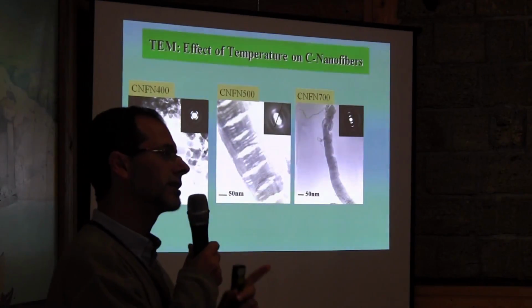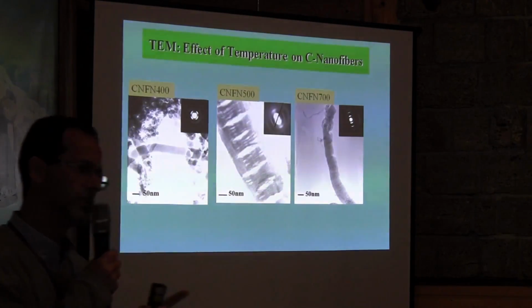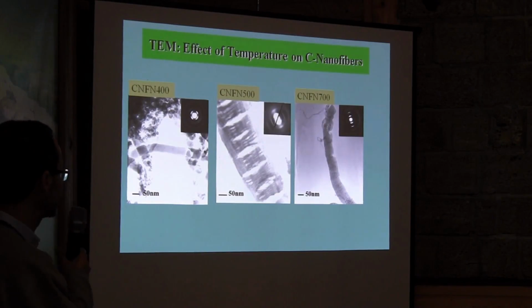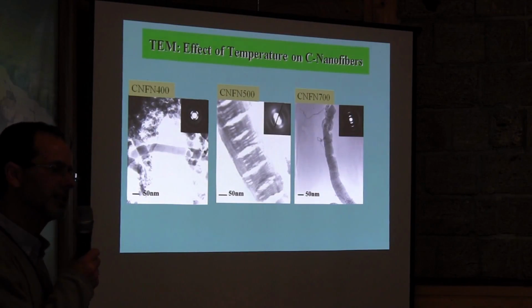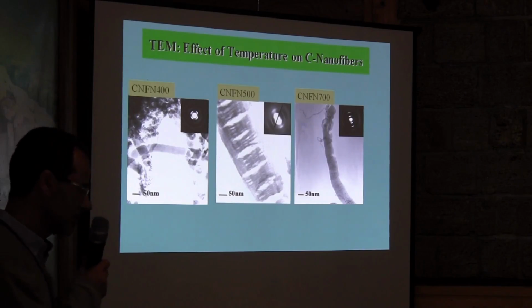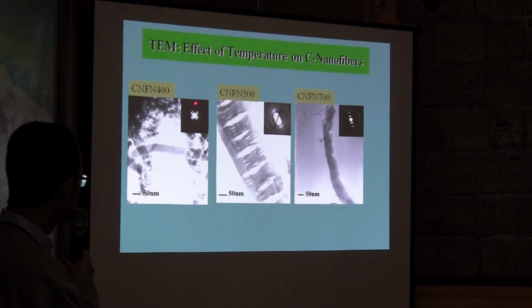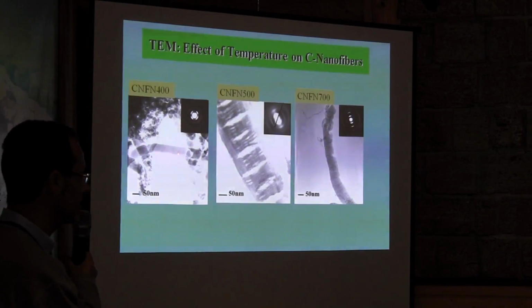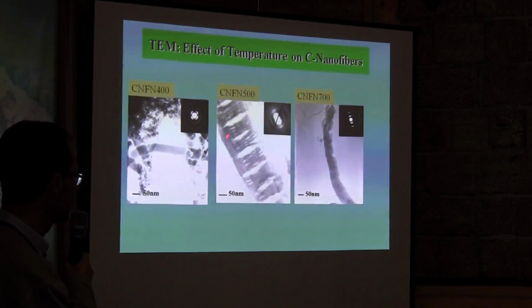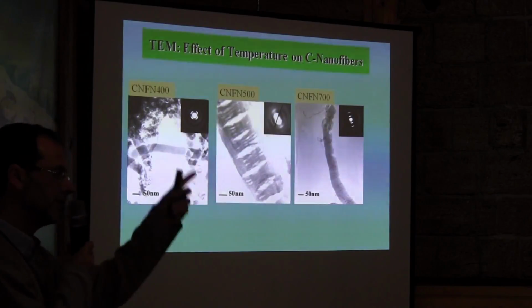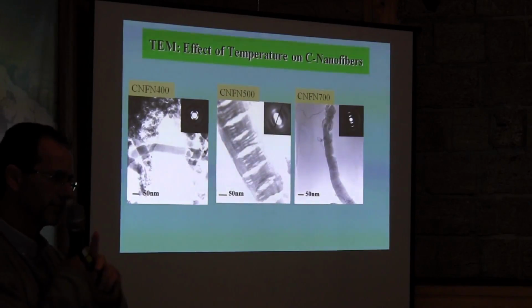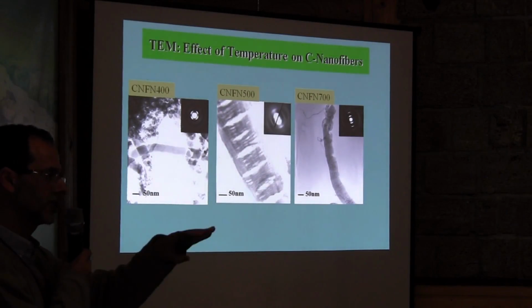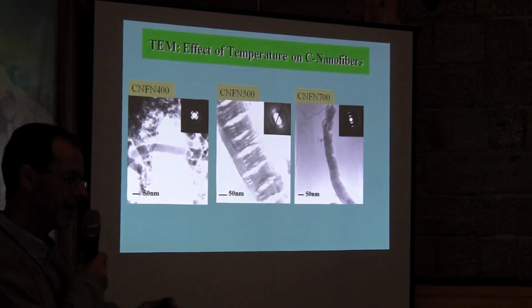Because I want to know the type of carbon nanostructure I have. So we do TEM, but we do also selected area diffraction, SAD. From this, if I make selected diffraction of this carbon at 400, what I can see is 4 spots. What does it mean, 4 spots? It means I have herringbone structure. So it's not platelet, it's not nanofibers, but it's herringbone.